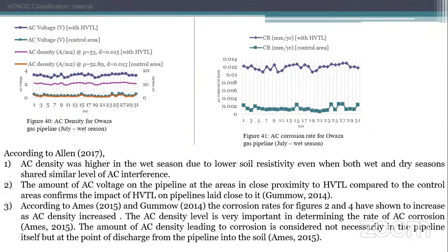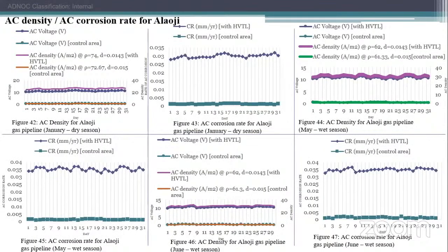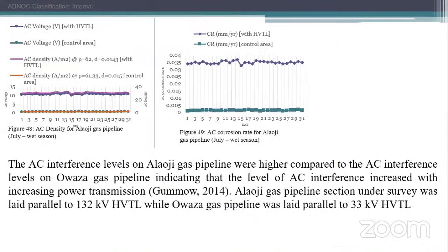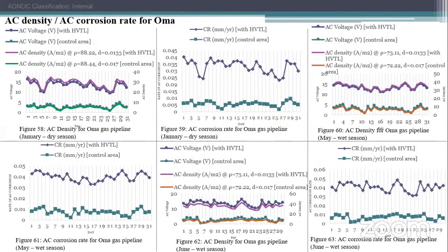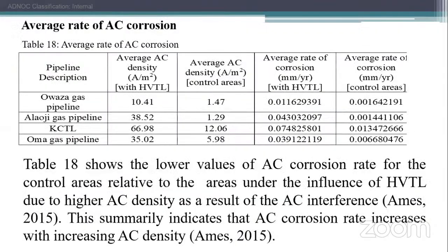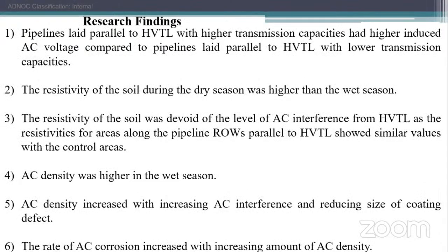We saw that for areas that were close to the high voltage transmission line, it had an effect on the pipeline. This happened for the 4 pipelines on which this study was done. But summarily, we can see the average rate of corrosion for areas that were close to the high voltage transmission line and the areas that were far away. The pipelines laid parallel to the high voltage transmission line had higher rates.